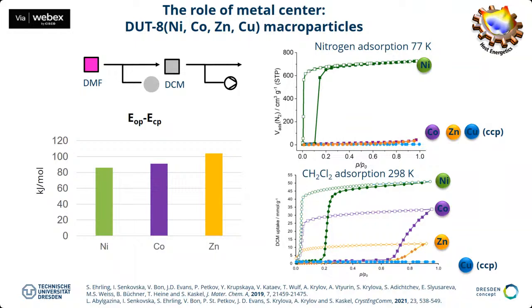And now we can understand how we come to functions also in these kinds of materials, because now we see selectivity. Because the energy difference is the smallest for the nickel, when you do nitrogen adsorption, when you look at the nitrogen uptake, only the nickel morph can be opened by nitrogen. But for the other morphs, cobalt and zinc, the energy difference is too high. Nitrogen does not have enough energy to compensate these energy differences, and therefore the other materials stay closed.